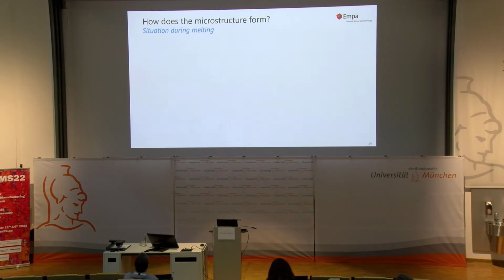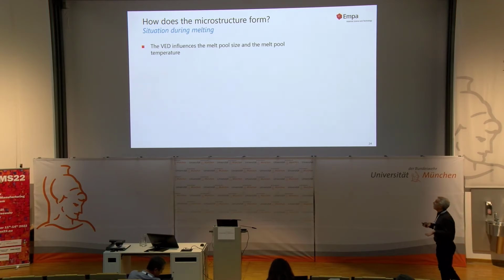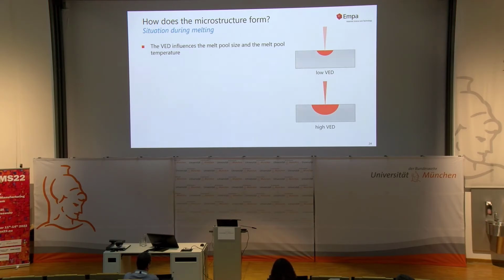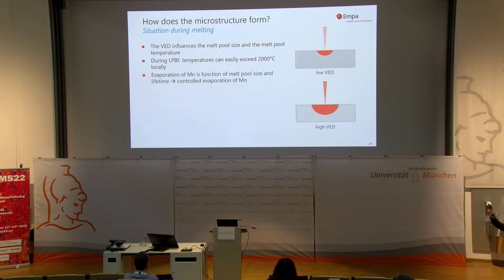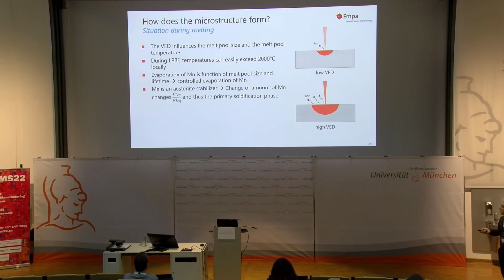Okay, what's going on? How does this microstructure form? Well, I think we can say that the volumetric energy density, so our laser parameters, influences the melt pool size and the melt pool temperature. So at low VEDs, we have these shallow, small melt pools. High VEDs create much deeper, much wider melt pools with a much bigger surface area. The temperatures, we know, can easily exceed 2000 degrees, go very high in the center, and we start evaporating manganese. Manganese is very volatile, it's known, and the amount of manganese that we're going to lose is a function of melt pool size and the melt pool lifetime. So here we lose less, here we lose more, and this can be controlled.